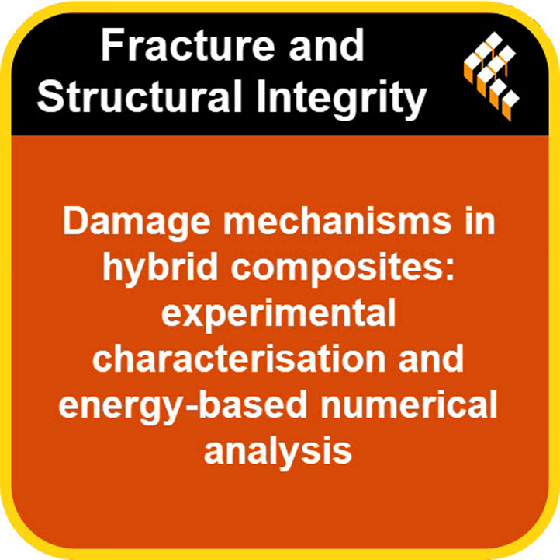Right, so they've built their virtual breaking lab. What did they actually see when they bent those different composite samples in the real world? Any surprises? Overall, they saw a pretty consistent pattern. The amount of force it took to bend the composites increased in a pretty straight line, linearly, as they bent it more, until it hit a peak. The maximum force. Right. After that peak, the force would drop off pretty quickly as materials started to fail significantly.